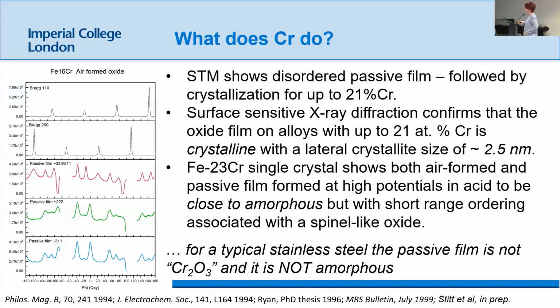And by the time you've got to about 23% chromium, the material is very close to amorphous. But we see this short range ordering both in STM and in diffraction. Of course, if you get to pure chromium, and we've also shown this, it's crystalline again. Right? So this disorder is to do with the competition between iron and chromium and how they form these networks in the oxide state.